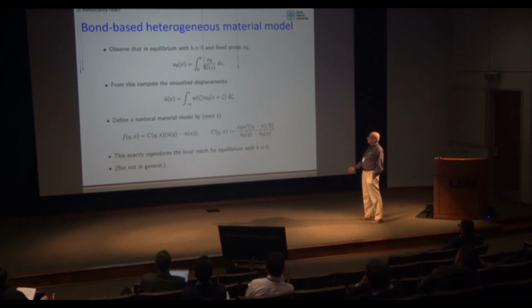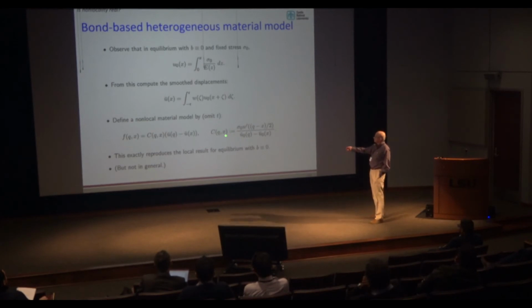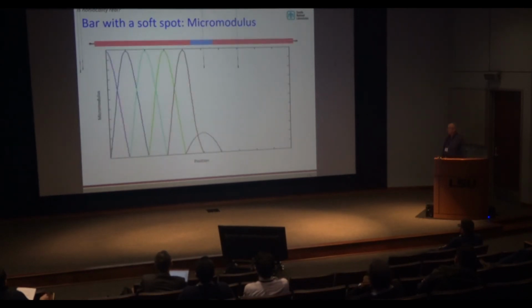And one way to define such a non-local material model is to observe that in equilibrium, the local solution has constant stress everywhere. Therefore, we can explicitly evaluate the local displacements, then smooth those displacements and define F to be this material property function, the micromodulus, times the difference in the smooth displacements at x and q. And if you define C this way, then this coughs up the exact value of sigma that you're looking for. So this is one way of defining a non-local material problem in this heterogeneous, smoothed heterogeneous bar problem.